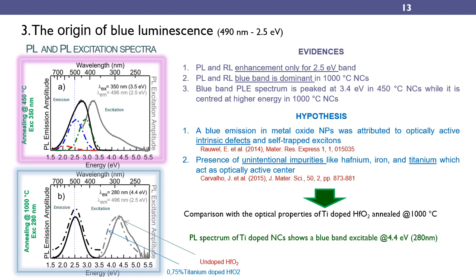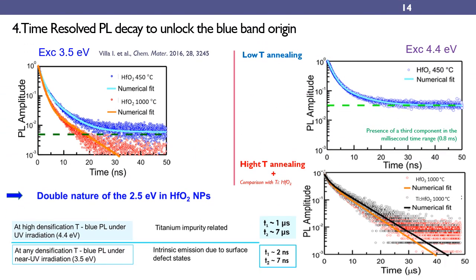On the contrary, by exciting in the near UV range, close to 350 nanometers, we can observe the intrinsic defect emission of hafnia nanocrystals. Time-resolved photoluminescence confirms the activation of titanium only in the largest nanocrystals under high energy excitation, with a lifetime of a few microseconds. Importantly, the results reveal the presence of an intrinsic blue band with a time decay in the nanosecond range in the smallest nanoparticles.